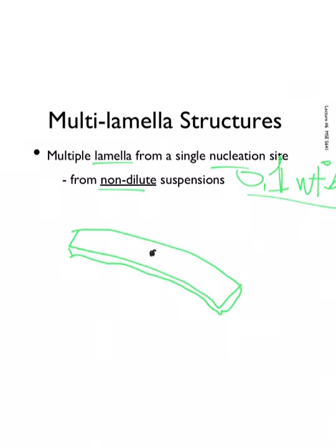Question, is nucleation and growth homogeneous or heterogeneous in real systems? Homogeneous, ideally. Heterogeneous in reality, in my experience. Heterogeneous in reality. Okay, so we have mathematical models for homogeneous nucleation. In reality, we don't know if we ever get there, because if a piece of dirt is 10 nanometers in size, who the heck knows if it's there or not? So it's really hard to prove you ever have homogeneous nucleation.